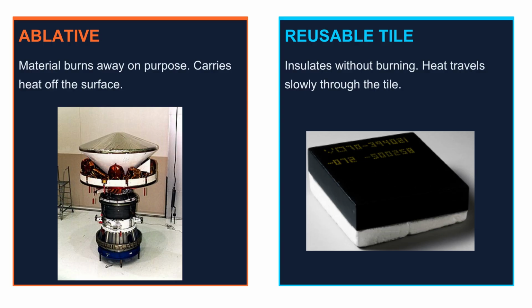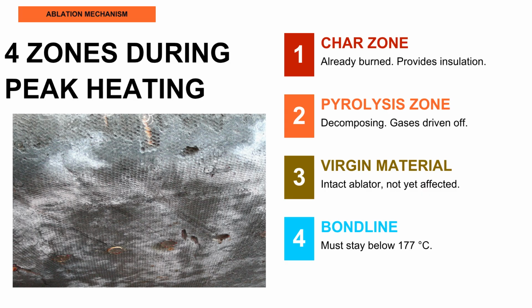Both strategies solve the same problem with opposite approaches. The right choice depends on mission requirements, entry speed, vehicle mass budget, and whether reuse is planned. An ablative heat shield has 4 zones during peak heating. Char zone, outermost layer, already burned. Provides some insulation. Pyrolysis zone, material is decomposing. Gases are being driven off. Virgin material, intact ablator below, not yet affected. Bond line, the interface with the spacecraft structure. Must stay below design temperature.